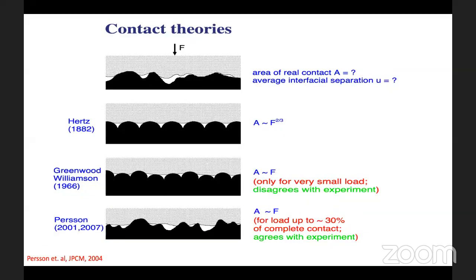I will now introduce Persson's theory and various contact mechanics theories. If you take two surfaces which are randomly rough, you will form contact like this shown here, and when you squeeze them you will have areas where you make contact and areas where you don't. When you count all the areas where you make contact, you can find the area of real contact from them. Then you can also find the average interfacial separation, the non-contact areas, which are very important in certain sealing applications. For example, there is a static o-ring which is in contact with a surface. Then the non-contact region is the region which decides where the leakage will happen, how the leakage will happen, and whether the leakage will happen or not.